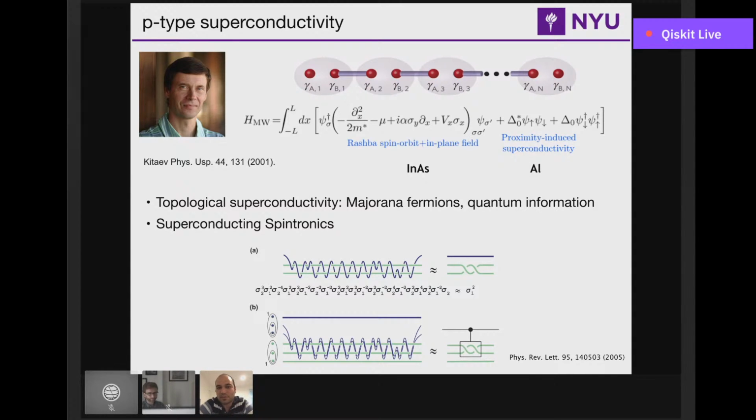We do not have all this in one single material, but I can find superconductivity in many materials, including aluminum, or spin-orbit coupling in semiconductors like indium arsenide, right? So maybe if I can put them together at that interface, I can borrow the properties of aluminum and indium arsenide. If the interface is perfect, there's a very good chance that I can create this state.